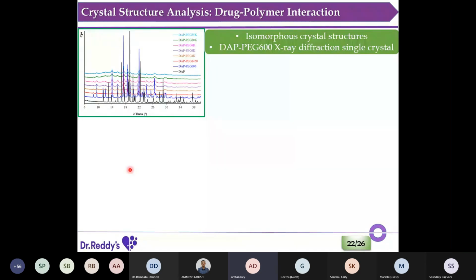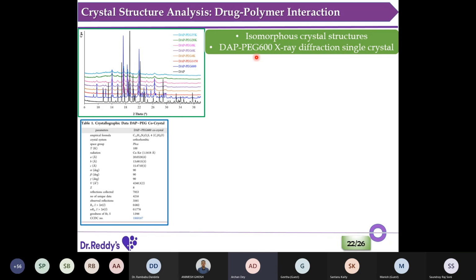Now you can see that I have already discussed all the different grades. Having the same pattern indicates they form an isomorphous crystal structure, meaning their unit cell and packing should be the same. We are getting the better crystalline material with the 600, which we indexed by powder XRD. We got a good cell dimension, and that gave us the strength to grow a single crystal, and luckily we grew one. The cell dimension and the stoichiometry match exactly with our proposal from the DSC.